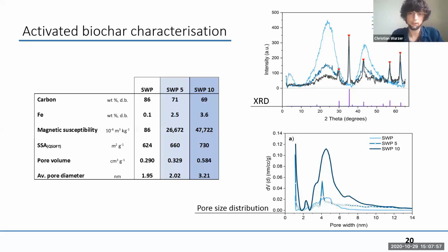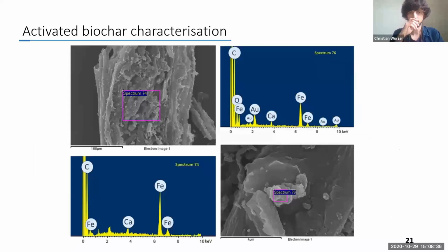Interestingly, the iron addition added pores in the size between 4 and 5 nanometers. So you can see in the peak of the dark line, as well as some micropores between 1 and 2 nanometers. The pores between 4 and 5 nanometers are especially important for biochars in wastewater treatment, because micropores are usually used in gas filtration. In wastewater treatment, you need some pores that actually allow the contaminant to reach the micropore to be adsorbed. So that's a very beneficial characteristic in this case.